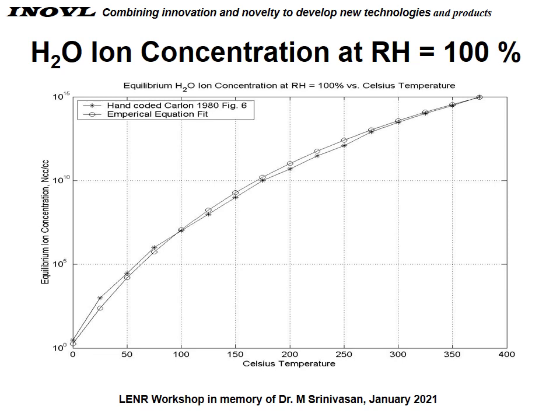We knew that relative humidity would also affect the conduction of gas based on some work that Carlon had done around 1980. We developed a plot of that around the temperature ranges we were using, and you could see that it was going up by several orders of magnitude. However, when we did our experiments, we were at least 3 orders of magnitude more conductive than what the relative humidity could account for.